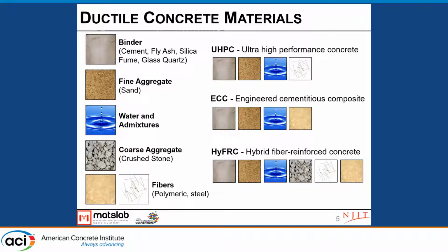We have very fine sand, water, and admixtures like superplasticizers and, in some cases, accelerators, and steel fibers. In engineered cementitious composites, we have, again, cement and SCMs like a large volume of fly ash, very fine sand, and water and some admixtures like water reducers and viscosity modifying agents, and also polymeric fibers. And hybrid fiber reinforced concrete is pretty similar to normal concrete. We have cement and SCMs, depending on the mixture design, fine and coarse aggregates like normal concrete, water and admixtures, and both steel and polymeric fibers.